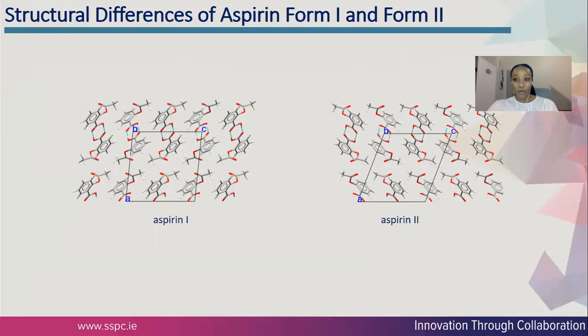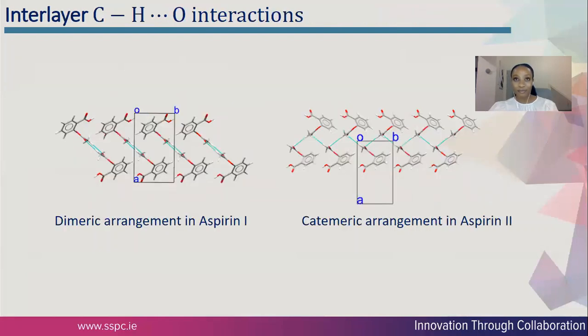Another aspect that is useful for purposes of establishing structure-property relationships is to compare the mechanical behavior of two polymorphic forms. In this case, it's two polymorphic forms of aspirin, to see how differences in the structure influence the mechanical behavior. The two polymorphs of aspirin feature very similar structural properties. They both have a centrosymmetric carboxylic acid dimer, but they vary in the arrangement of these dimers and the resultant interlayer interactions. The distinction between the two polymorphs is seen with the arrangement of the interlayer CHO contacts.